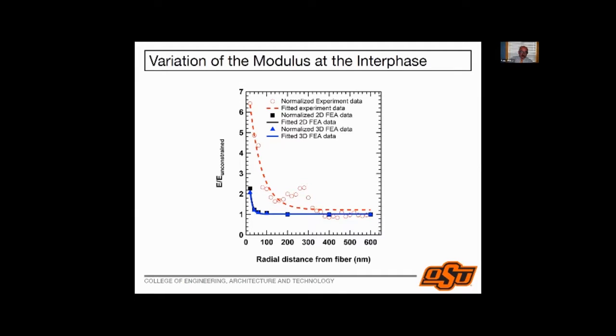So backtrack before we get lost completely. I have a carbon fiber, I have an epoxy matrix, I have an interface between the carbon fiber and the epoxy matrix. I carry out an indentation experiment which tells me the elastic modulus. I don't know if the elastic modulus is going up because of the constraint effect or because the properties themselves are changing. So I carry out a finite element simulation in which I can look at this ratio, E divided by E unconstrained, and I get this line on the bottom. So all of these lines on the bottom, the last 4 data sets over here, are from finite elements, 2D or 3D. And this red line is a fit to the experimental data that we get.